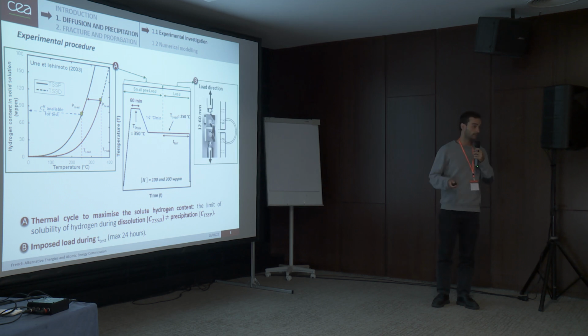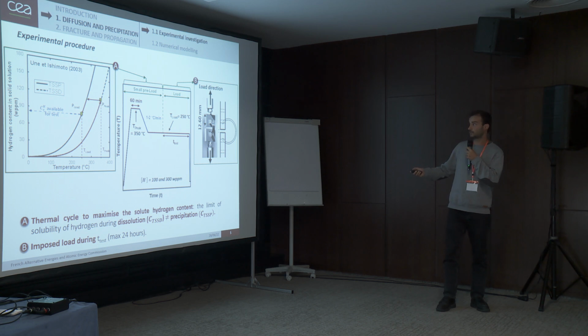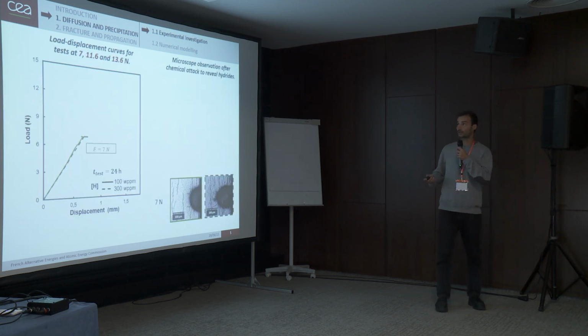The second step is a mechanical phase, where we apply a load to our specimen, which is placed into two slotted springs in order to limit friction during the test. This load is applied during a test time, and if nothing happens after 24 hours, the test is stopped. So I'm going to show you some results.